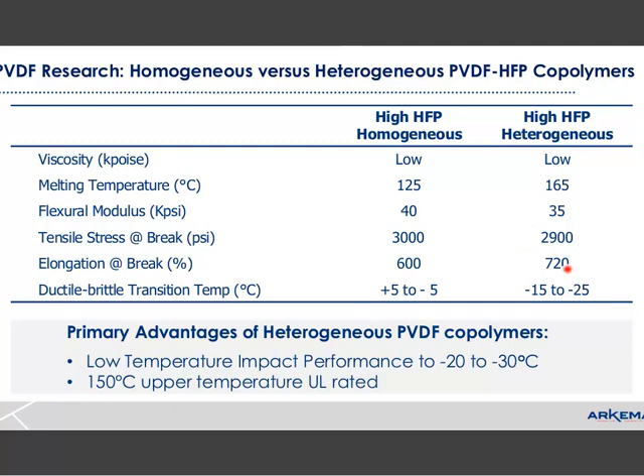In general, though, we do find that the heterogeneous products do tend to have higher elongation at break, and they tend to be a little bit more ductile. And most important, the ductile brittle transition temperature is significantly reduced, and in this case, down to about -25 degrees C.